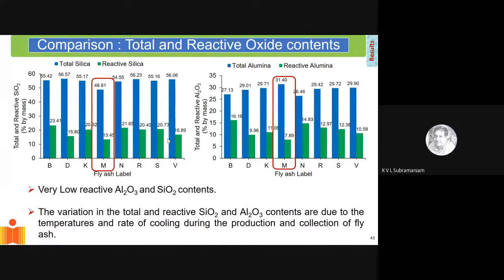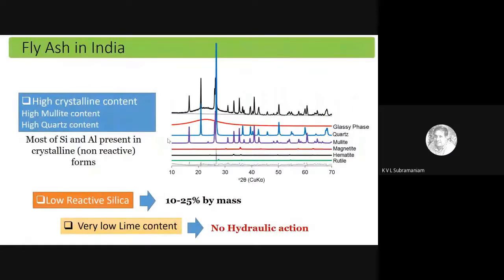So if I take some fly ash or any supplementary cementitious material, I need to identify the amount of silica that is present in this reactive form. Then I can start looking at cement replacement in an efficient manner. Just to reiterate, I wanted to emphasize that material characterization is very important. If you give me any material, and if I want to use it in cement chemistry, I have to look at the primary ingredients in terms of its oxides. When it comes to primary ingredients, I'm primarily interested in calcium, because it's calcium silicate chemistry. And I'm interested in the silica, but I need to identify the form of silica. I'm interested in the reactive form of silica, which can then be used to form calcium silicate hydrate. And that is the strength-giving material of cement.